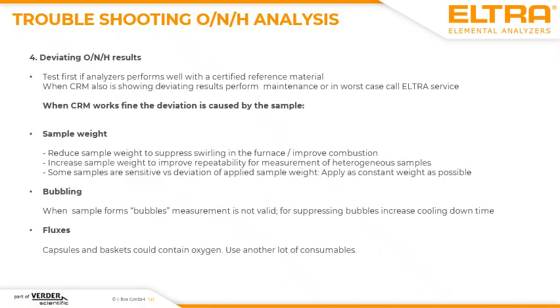The most demanding challenge in ONH analysis is always getting rid of deviating results. When you are getting deviating results for your powder, the first step is always to run a CRM for controlling the analyzer. This means when you are getting deviating results from your sample, please go back to the CRM and check if the analyzer is working properly. When the CRM can be analyzed according to its definitions, then start with evaluating single steps,